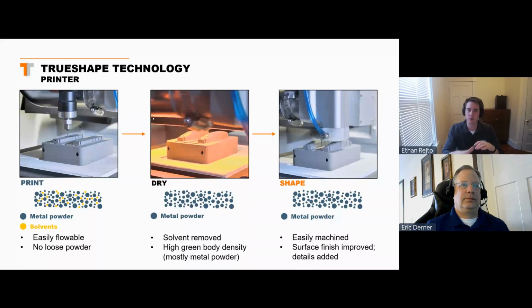After you've printed one layer, you're going to come across and dry that layer. Here we're removing the solvent. The metal powder is actually going to settle a little bit, and the result is a high green body density. What does that mean? It means that you mostly have metal powder, tightly packed metal powder, that you have a very high density of metal powder in your part, and we've been able to remove most, if not all, of the solvent from the part at this stage.